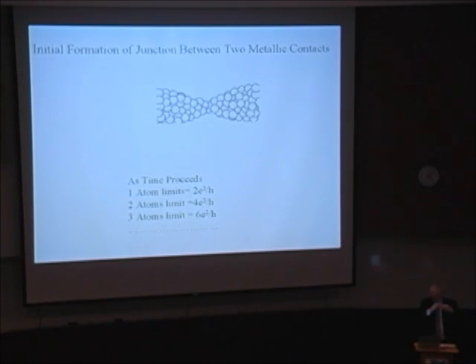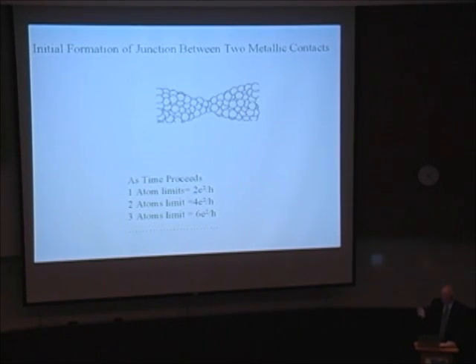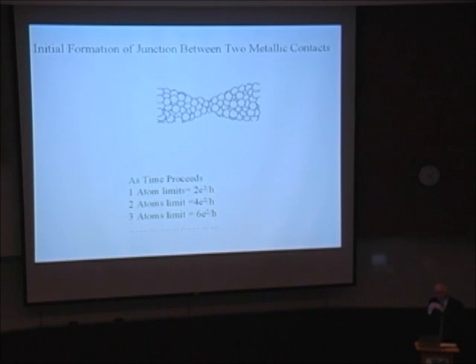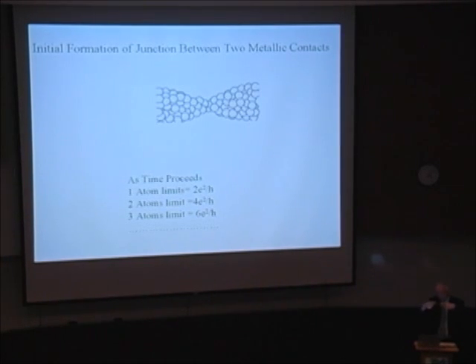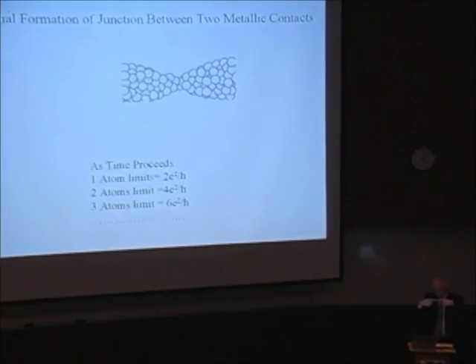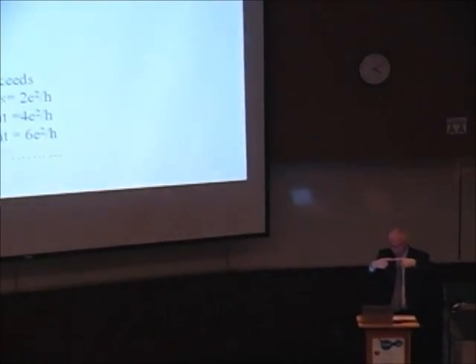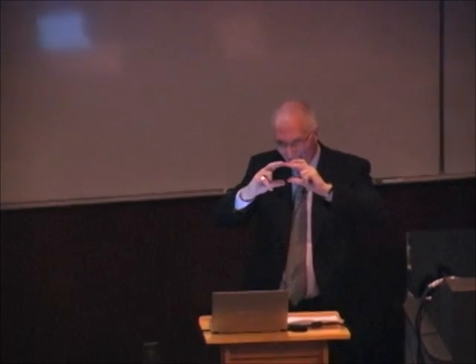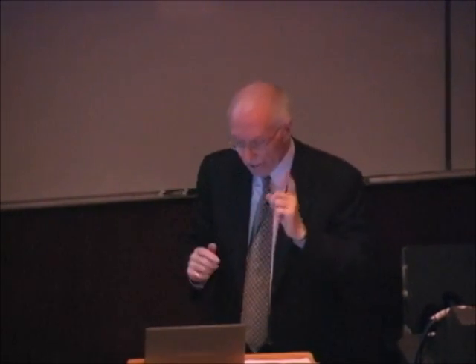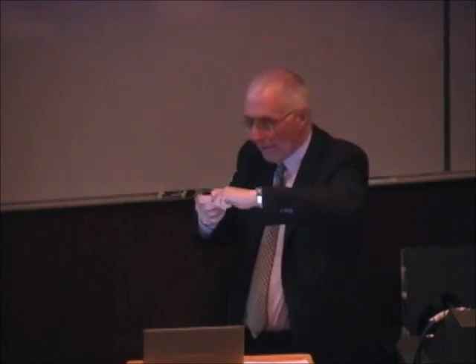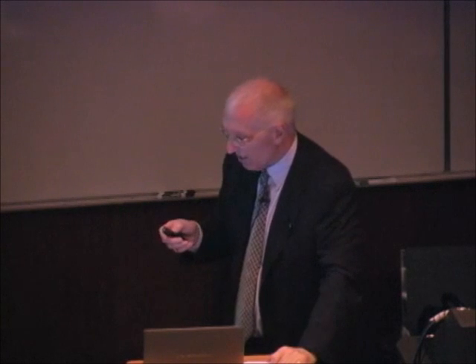But just before it snaps, the conductance goes as 6e²/h, 4e²/h, 2e²/h, because of the number of atoms in contact. If we've just got two atoms like that, then we get a conductance of 2e²/h. If we have like that, then it's 4, and if we have like that, 6. And you can actually see this in an experiment. You just pull the wire apart. This is room temperature, set up in the lab, and you can just see those steps on an oscilloscope.